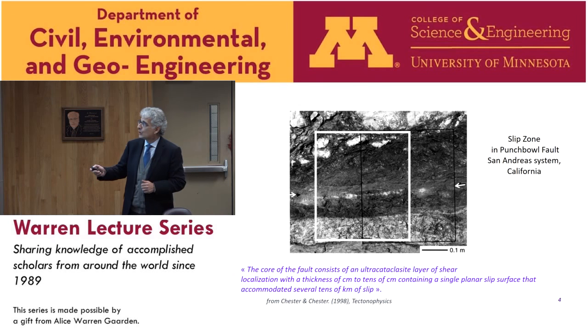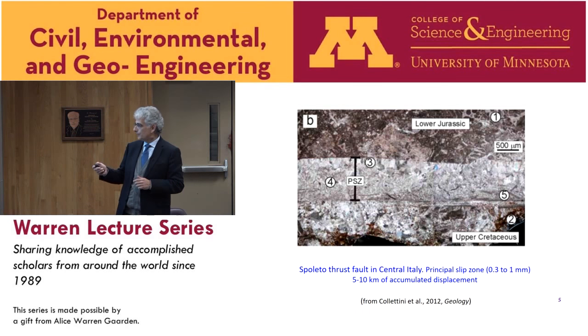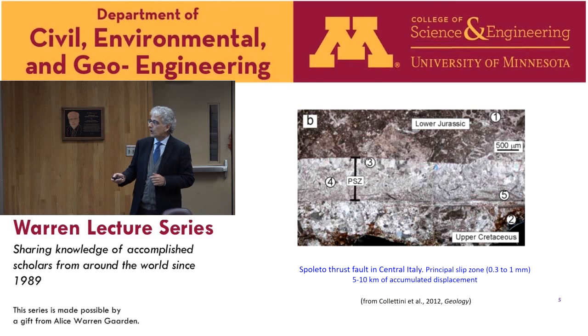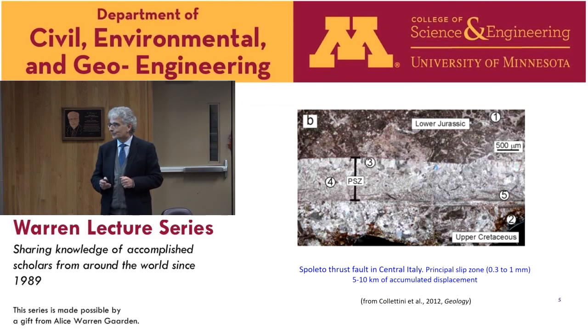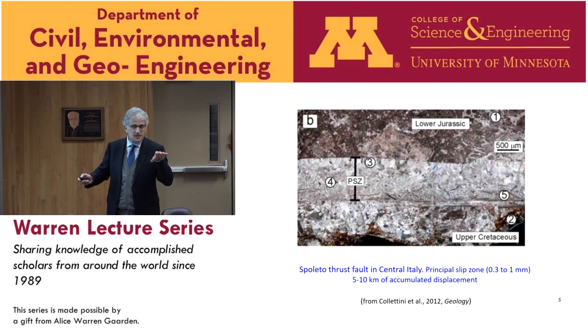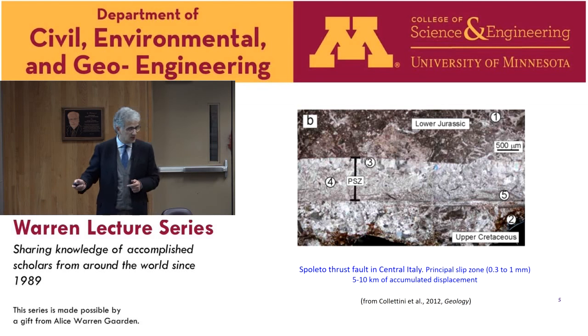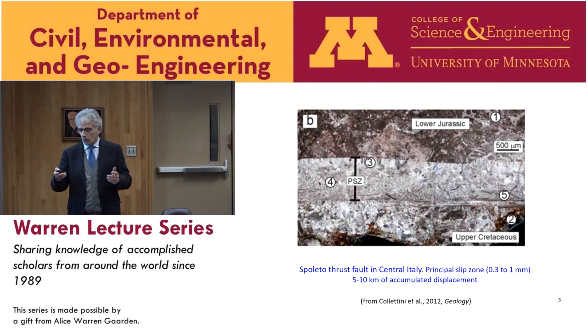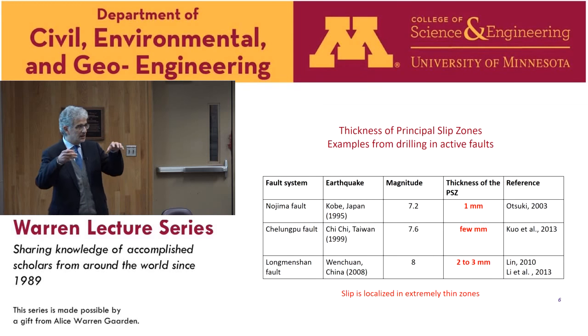Actually, if we look more closely, this is not a surface, but rather a zone. This is, for example, documented in an outcrop of a fault in central Italy. I took this picture from the paper of Collettini, where this slip zone, which is called PSZ, principal slip zone, is seen here. You see the scale, this is 500 microns. So the thickness of this principal slip zone is actually a few hundreds of microns, and it has accommodated 5 to 10 kilometers of displacement.